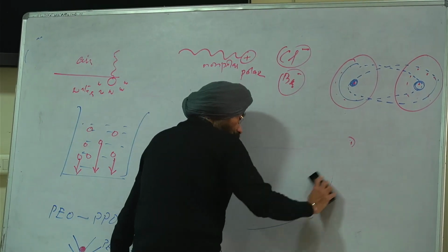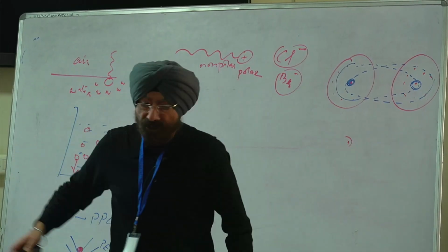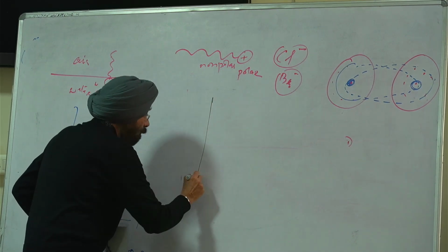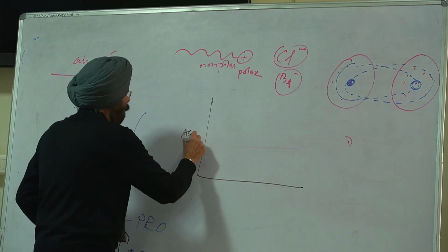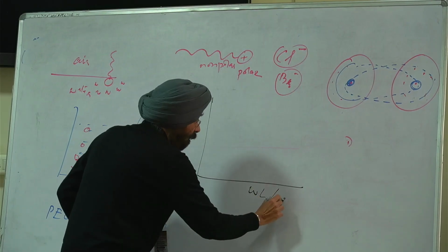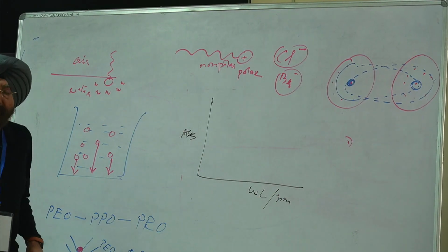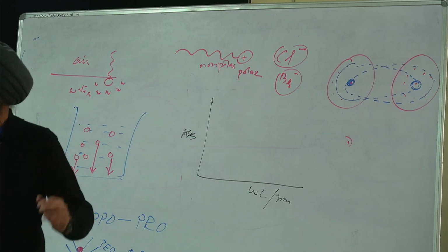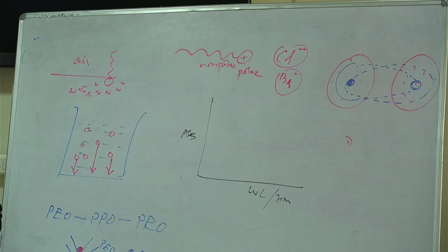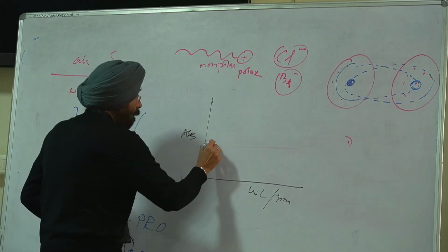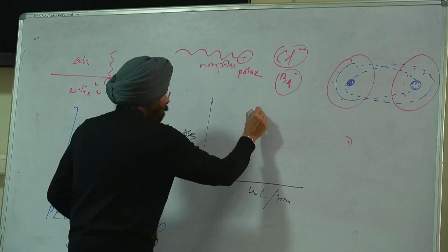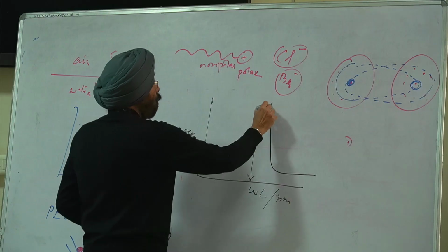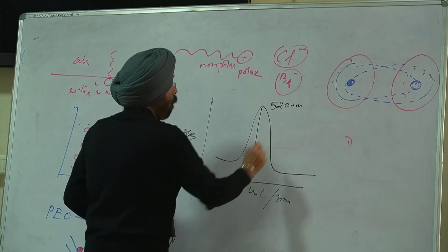So you see over here the UV spectrum, which is slightly complicated, so I'm going to explain it in 1 minute. This is the UV spectrum, absorbance and the wavelength in nanometer, right? For a red color gold nanoparticle suspension, the one which I showed in the first few slides, you should have the absorbance something like this, and this should be close to 520 nanometer.